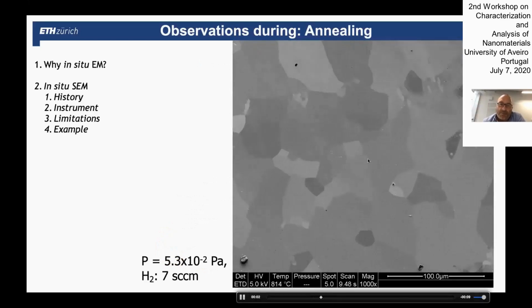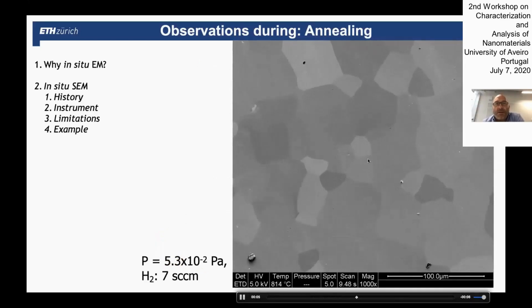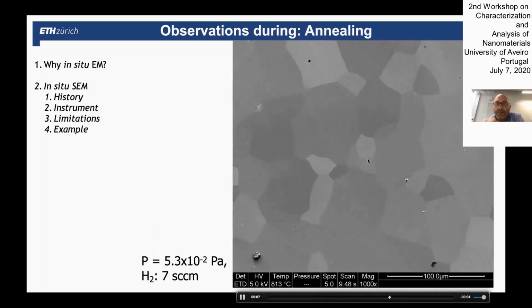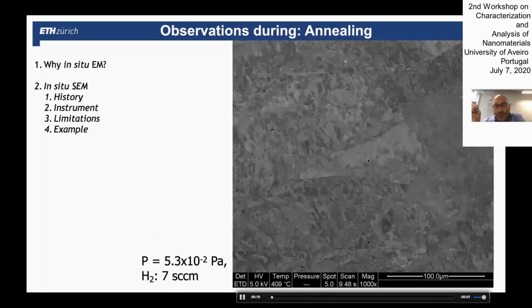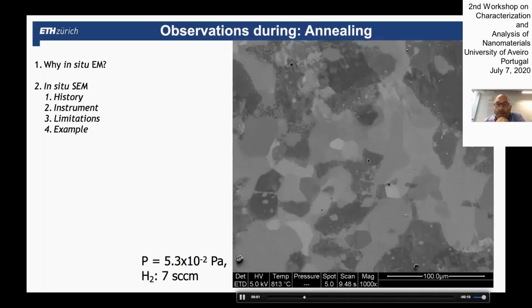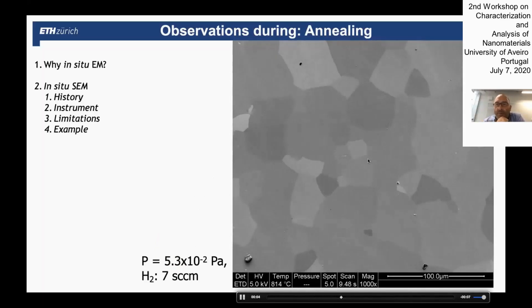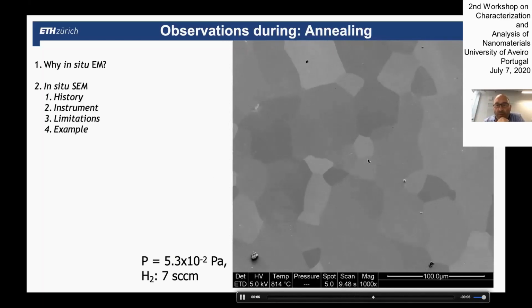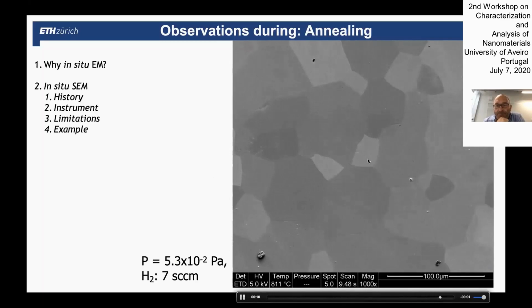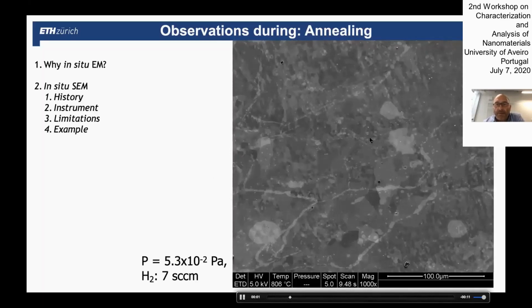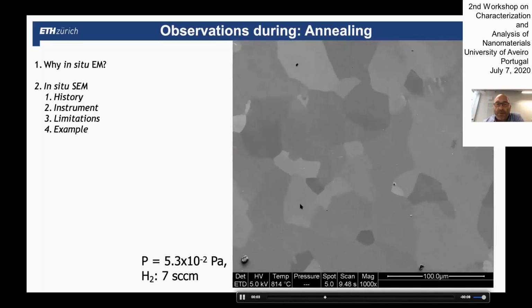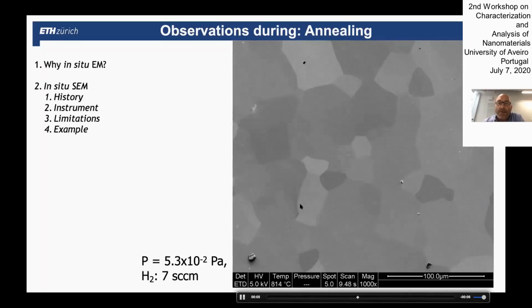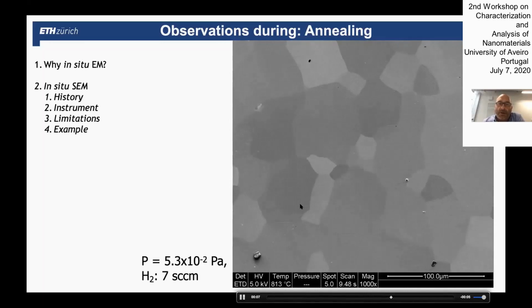The first thing we need to do is to clean the catalyst surface. It's a metal, in this case we used platinum, and just the cleaning alone is something beautiful to watch. We start with a polycrystalline foil, which was initially quite dirty. In this video, at about 800 degrees in hydrogen, you see at the beginning that the surface reconstructs. You see beautifully how the surface cleans up, how some low energy grains grow and other grains disappear, so you have some abnormal grain growth.